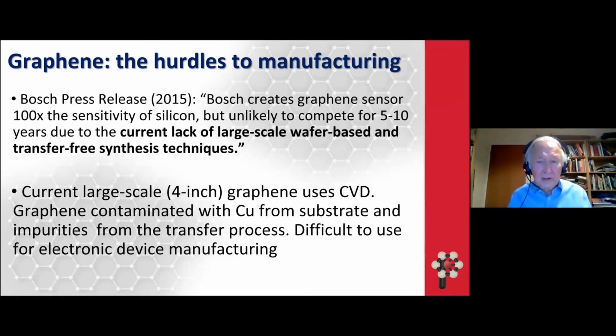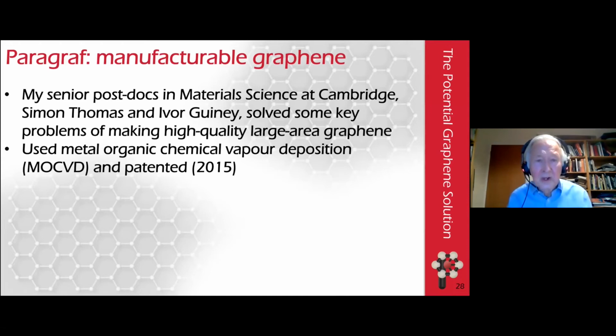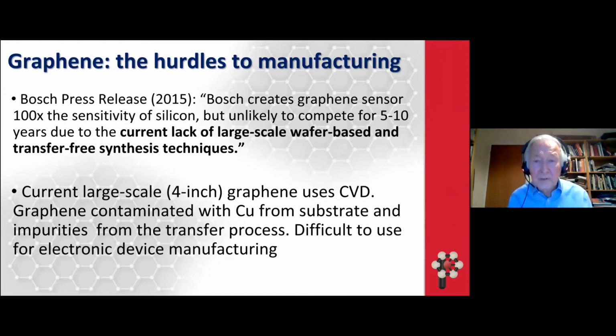And large area graphene was then available and is still available using a technique called CVD, that's chemical vapor deposition. But what's done in that technique is the graphene is made by depositing gases like methane on copper, and the copper is used as a catalyst to decompose the gases and deposit carbon. And so the carbon then, which forms graphene, has copper as an impurity in it. And then if you want to use that graphene, you have to transfer it from copper to a more useful substrate, and you get impurities from that as well. So it's really difficult to use this for manufacturing electronic devices.